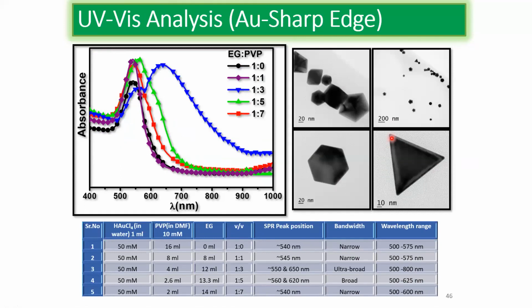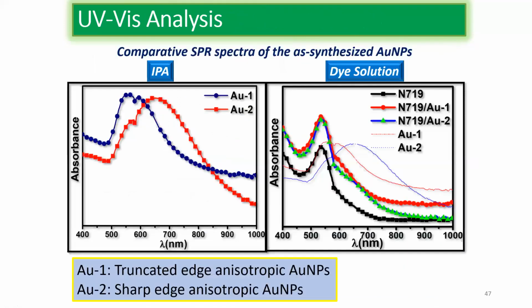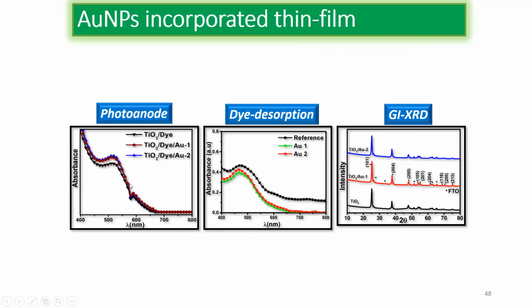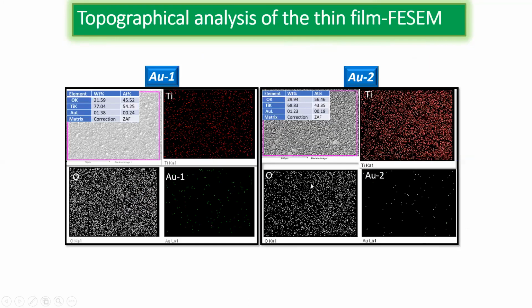Sharp edges are very, very useful because they create a hotspot. Here the plasmonic resonance will be very high, so this material should show even better results. So I used this material. I applied it into the dye, into the photoanode, and studied different XRD characterizations, and this is called the EDAX mapping.